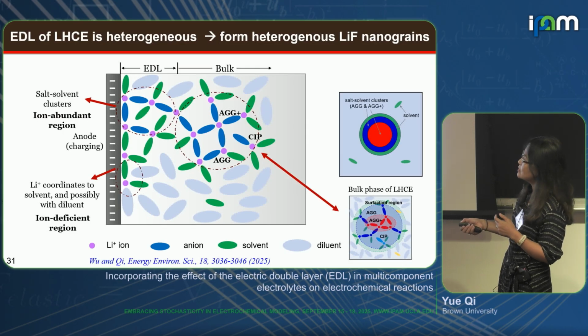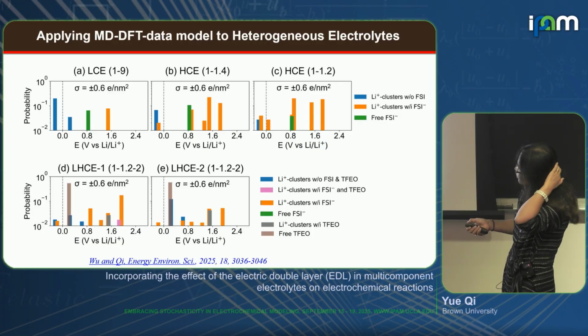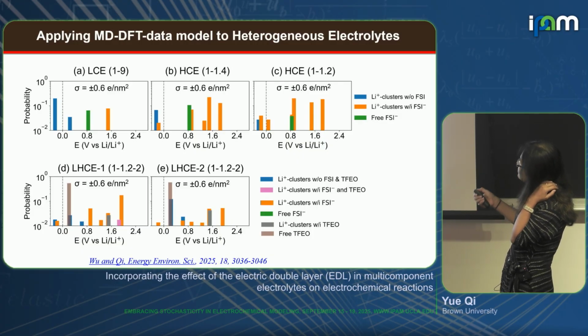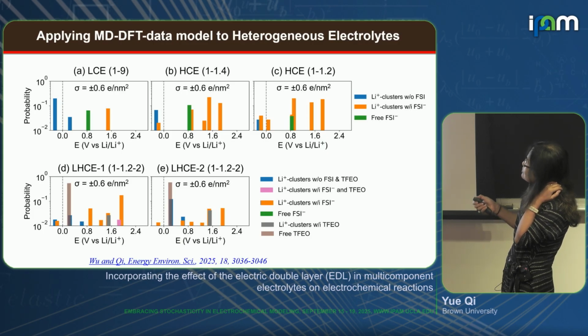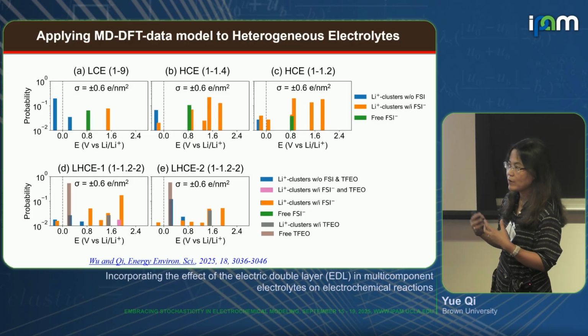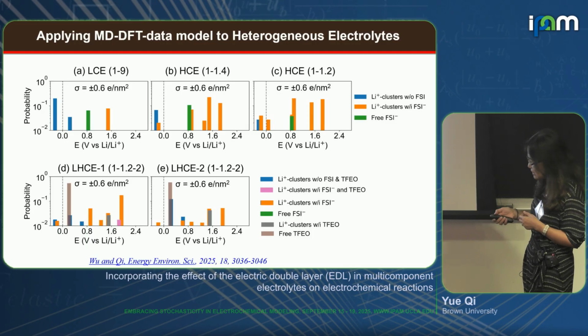Because we also have fluorine species from them, the ions will contribute some fluorine species. And that is more like our counting of different species that get reduced from low concentration to high concentration to this localized high concentration. So basically at low concentration, we see some ion contributions, and with the increase of concentration, more and more of the ions start to contribute, being reduced. And then when you add this diluent, the TFEO also contributes a bit to our fluorine species, so you get more diverse lithium fluorine grains near the interface.